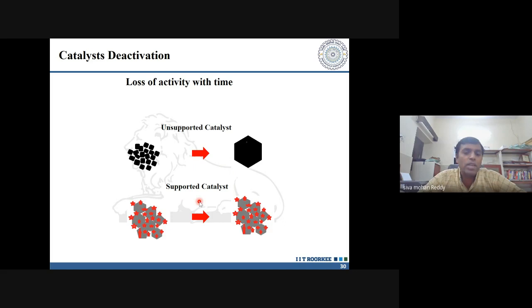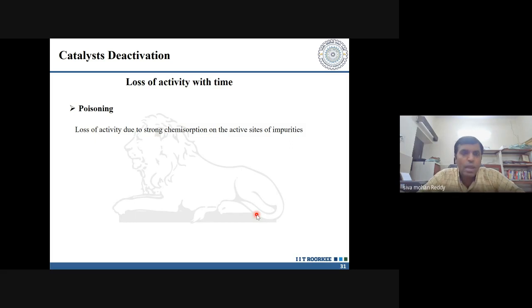Now the second thing is if you have a supported catalyst. If you have a variety of supports and you have a catalyst supported onto your support, that might be aluminum, carbon, or any of the materials that you are going to look out for, these also will lose activity. The carbon gets deposited over these active sites and thereby reduces the activity of your catalyst. Now the other key problem that happens during this catalytic process is that you lose activity because of chemisorption. That means some of the intermediates might come and sit on the active surface or the active sites of your catalyst, and thereby reduce its activity.